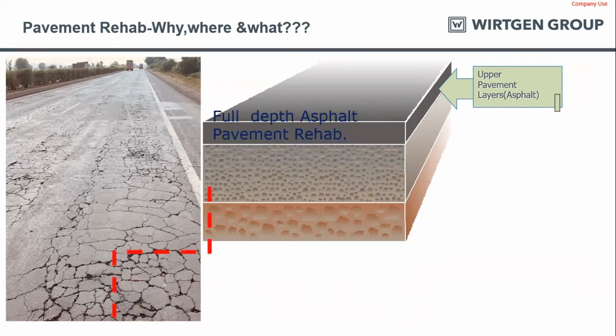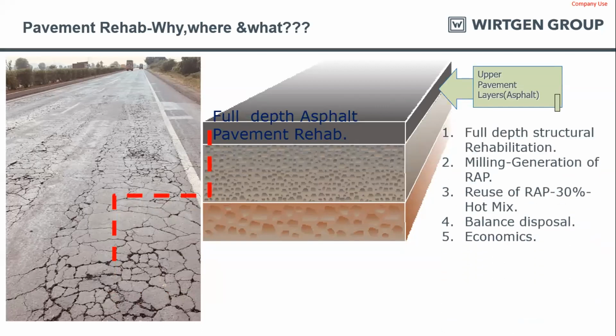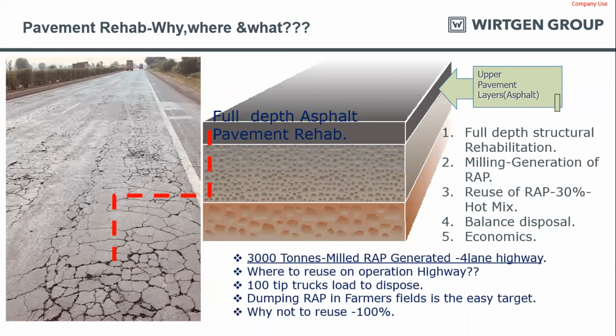One option you have is to mill the existing damaged asphalt layer using a milling machine, and then you can reuse 30% of it back into the hot mix. The code allows 30% reuse in the DBM layers, but the question arises what you will do with the remaining 70%. Whether you are going to dump it or dispose of it in nearby areas, again it causes environmental problems. So the question arises, why can't we use 100% of RAP back into the system?